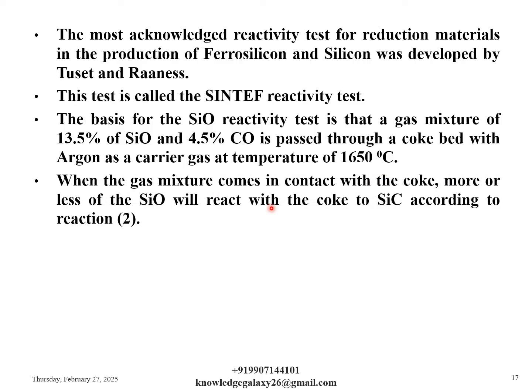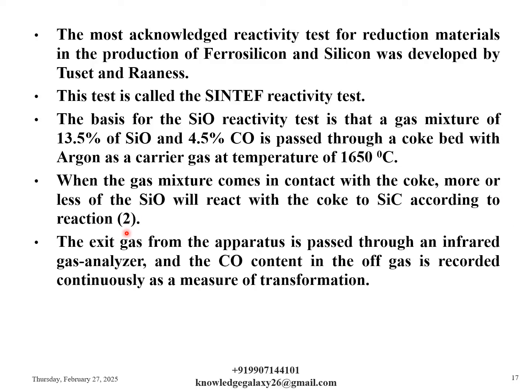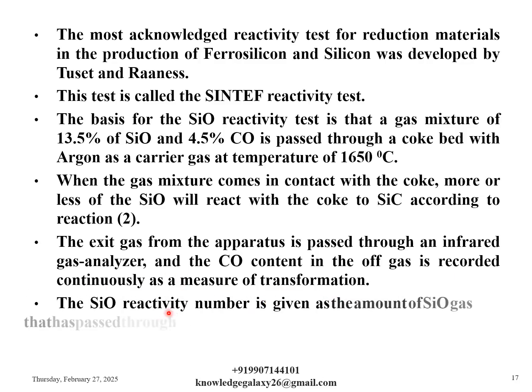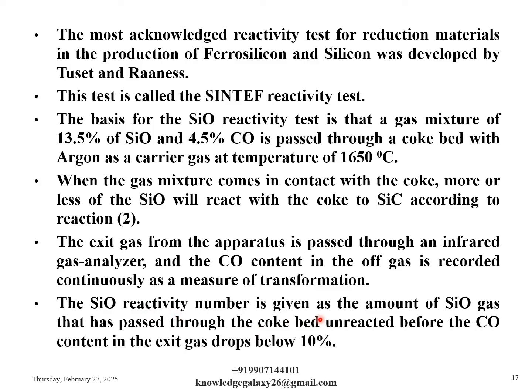When the gas mixture comes in contact with the coke, more or less of the SiO will react with the coke to silicon carbide, SiC, according to reaction number 2. The exit gas from the apparatus is passed through an infrared gas analyzer and the CO content in the off gas is recorded continuously as a measure of transformation. The SiO reactivity number is given as the amount of SiO gas that has passed through the coke bed unreacted before the CO content in the exit gas drops below 10%.